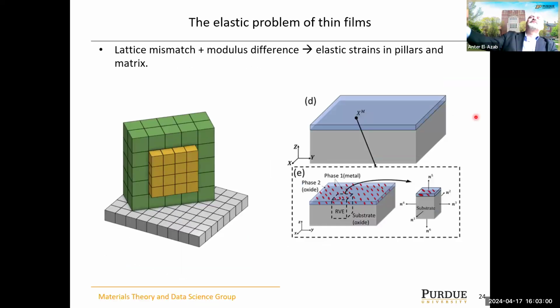This brings me to the next modification of this method, which is, if we have multiple materials and there is a significant mismatch in lattice parameters and so on, and there are elastic strains coming due to this mismatch in the system, how does this elastic strain influence the diffusion and self-organization kinetics on the surface?